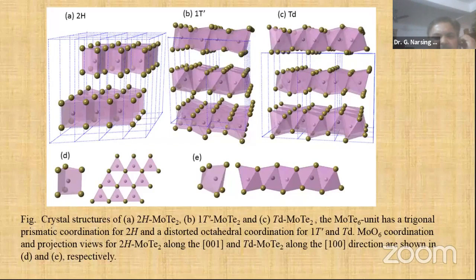Okay, so these are the Crystal Maker pictures of 2H, which is a hexagonal structure. This is 1T prime, a monoclinic structure. This is Td, also monoclinic, but the space group is different. So there is a phase transformation from 1T prime to Td with decreasing temperature. Okay, so there is a phase transformation.